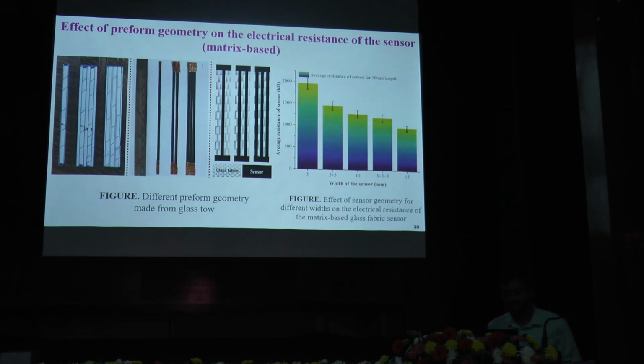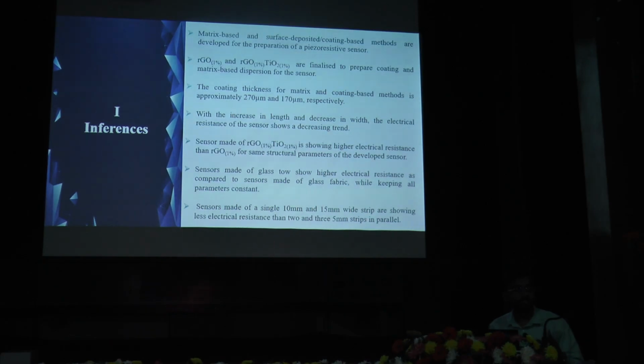Further, we tried to change the geometry of the sensors and put this particular sensor in the composite material. We understood from this experiment that with increasing length and decreasing width, the electrical resistance of the sensor shows a decreasing trend, and sensors produced using the glass tow show higher electrical resistance compared to sensors made from glass fabric, while keeping all parameters constant.